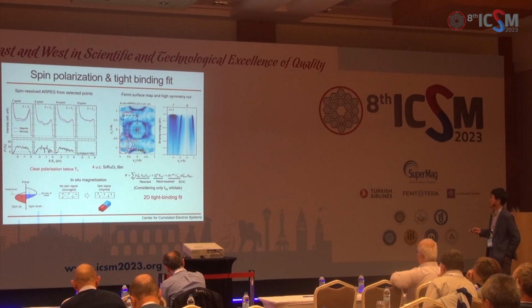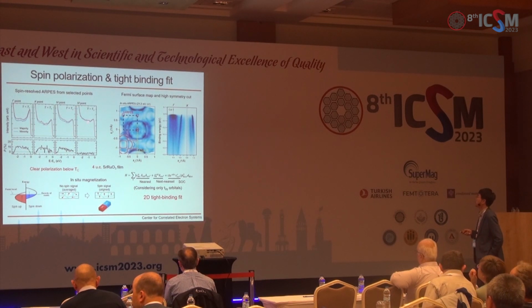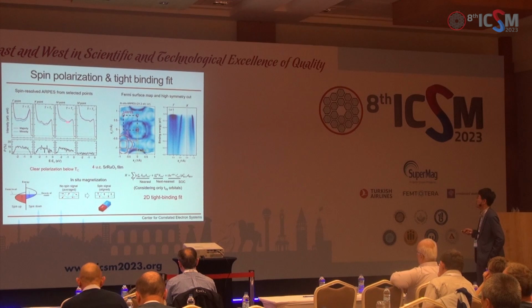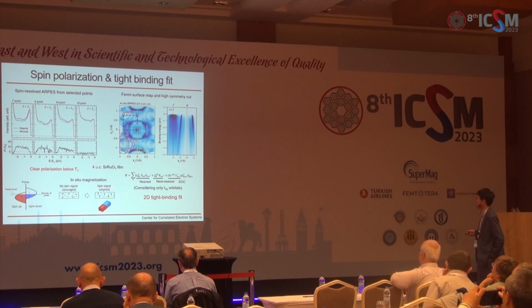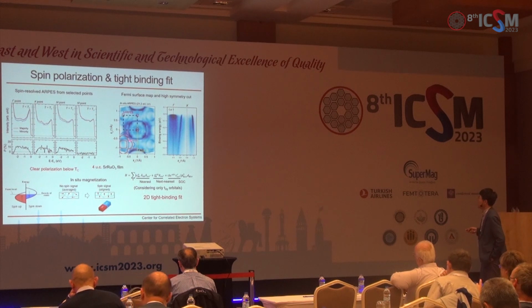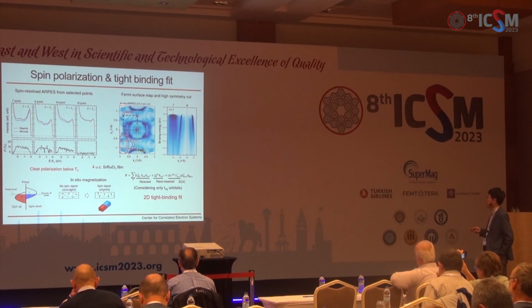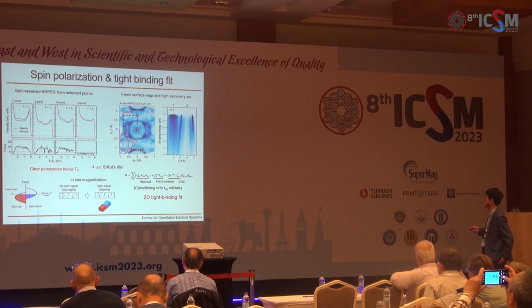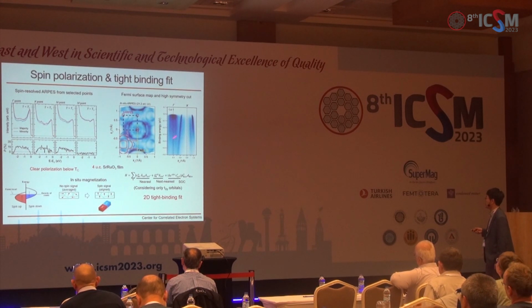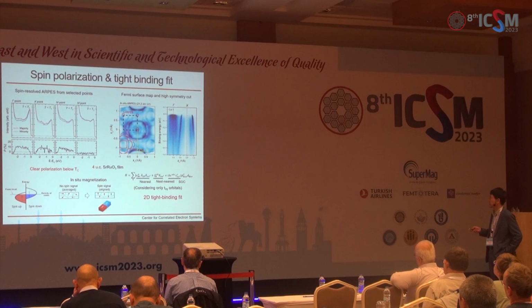So here we perform spin ARPES first. Above TC, we don't see any spin polarization, but below TC, we see spin polarization at different parts of the Brillouin zone. And to do that, we magnetize the film in situ also. Now, we can also measure the Fermi surface map, as shown here, in situ, and we can use a tight binding model to fit the experimental dispersion using this model here. By analyzing this 2D tight binding fit of the data, we can find topological properties of these bands.